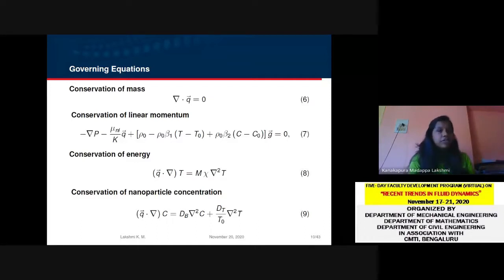So moving on to the mathematical formulation, the equations governing the problem are the conservation of mass, linear momentum, energy, and nanoparticle concentration, which are modeled for the nanoliquid saturated porous medium using a modified Buongiorno-Darcy model. The choice of the modified Buongiorno model is because from it we can obtain the results of the KVL single phase model as a limiting case, because the nanoliquid can be modeled using the KVL single phase model and the Buongiorno two phase model. The difference between the two models is that